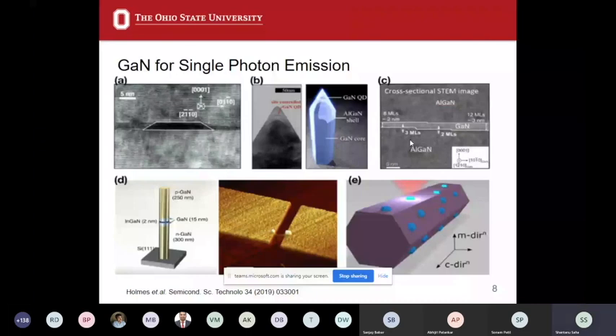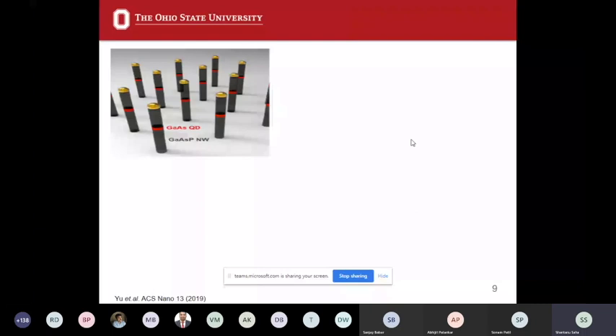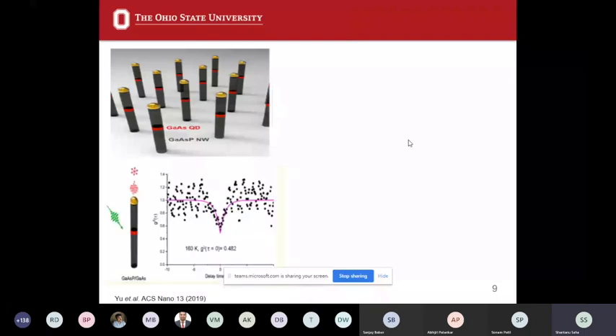So apart from hBN and GaN, people are also working with gallium arsenide quantum dots and gallium arsenide phosphide nanowires. So these kinds of structures are also there. But why are we looking at quantum dots for single photon emitters? Because a quantum dot is 0-dimensional. As you know, a nanowire is 1-dimensional, a quantum well is 2-dimensional, bulk material is 3-dimensional, but as a quantum dot is 0-dimensional, it has very high exciton confinement energy, due to which it will have a very high emission rate, narrow emission line width, and high fidelity anti-bunching.